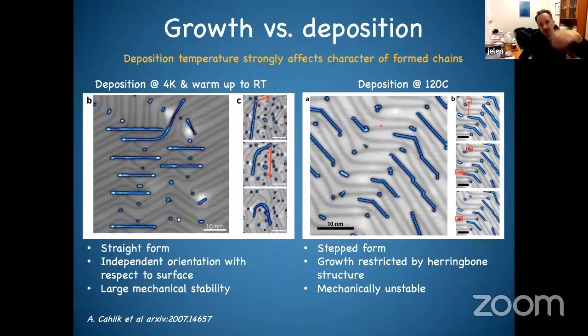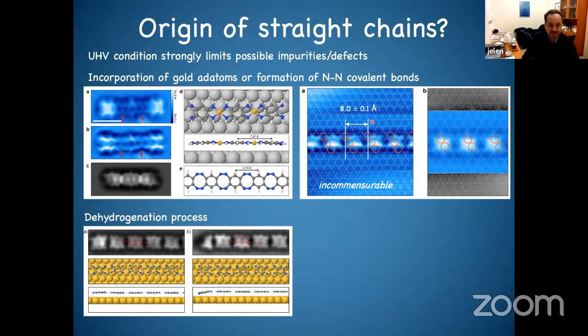So what could be the explanation here is that when we deposit them at a higher temperature, we have more defects, and it means more dehydrogenation, and these chains are unstable. But that's an observation. We don't have a strong argument for that. But there is one more thing behind the difference between these two.